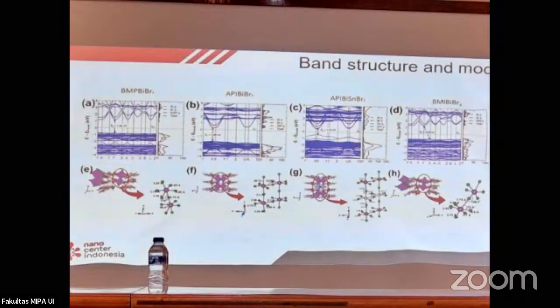And then to understand a bit, we asked for help from Haris, ITB, to calculate the system. And from the band structure, all the energy, the band gap, looks pretty much in agreement with what we found from the UV-Vis spectrum after correction by Elliott formalism due to the excitonic features. And then the most important is basically on the bottom panel.